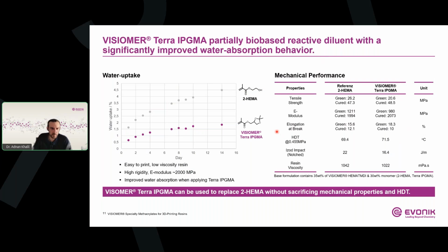And beyond the mechanical performance, the Terra IPGMA also provides a significant advantage in terms of water uptake behavior. So as shown here on the left, the formulation containing the Terra IPGMA absorbs substantially less water over time compared to the corresponding HEMA system. And the reduced water absorption can contribute to improved dimensional stability, better retention of mechanical properties under humid conditions, and an enhanced long-term durability of the printed components.